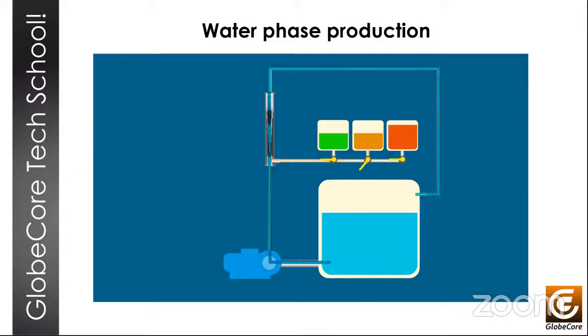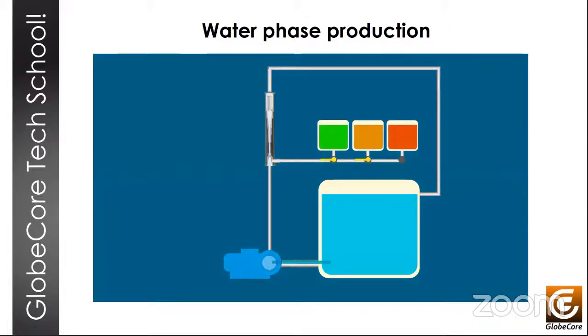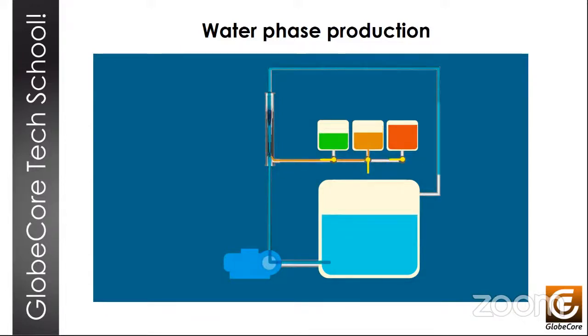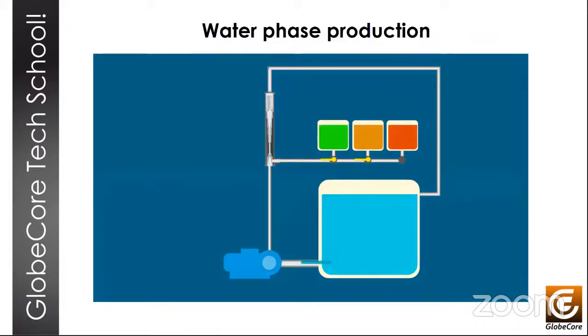Another advantage of this process lies in the fact that the plants can work longer using one batch of water phase without the need to use large containers for blending, because the concentrate of the water phase is diluted by as much as 5 times before entering the emulsion mixer with just regular water. In addition, the mixer allows to take some physical load off the mill, which serves mainly to stabilize the already mixed emulsion. And this becomes apparent in terms of quality of the emulsion produced and in the lifetime of the mill itself, because less wear.